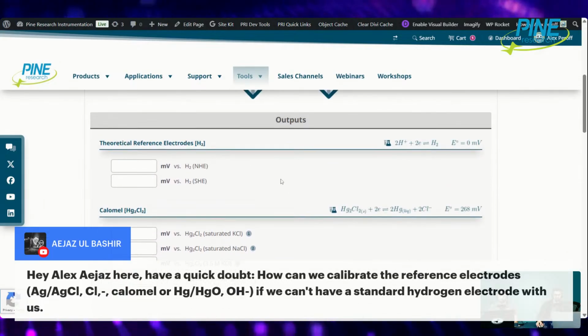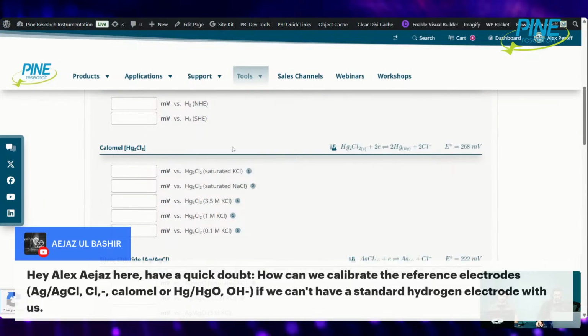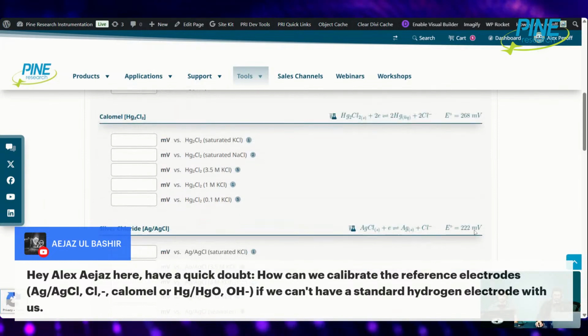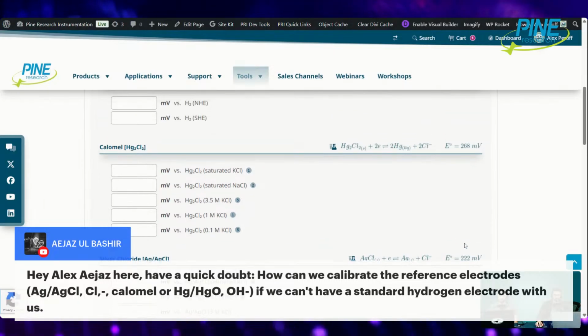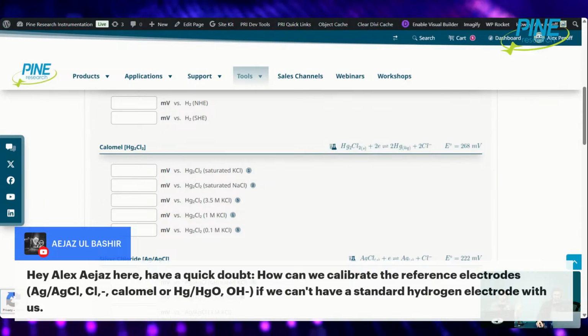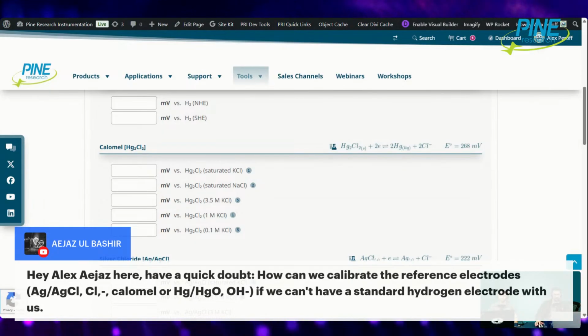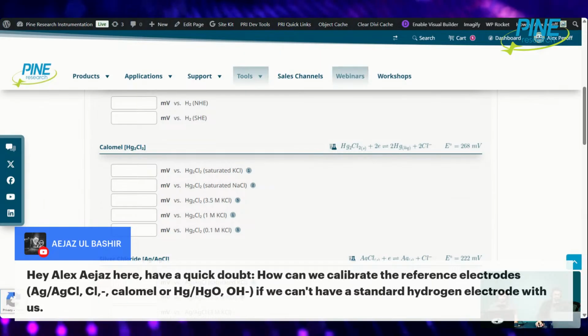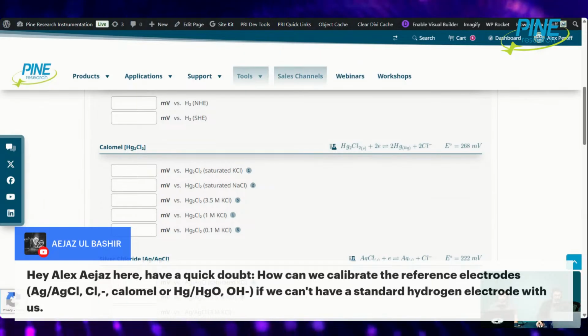So calomel is here. Its E0 is 268 millivolts, and silver chloride is 222 millivolts. You would just look at the difference between these two. I'm going to use a calculator very quickly. 268 minus 222. You should get approximately a 46 millivolt difference when you do this open circuit potential experiment.